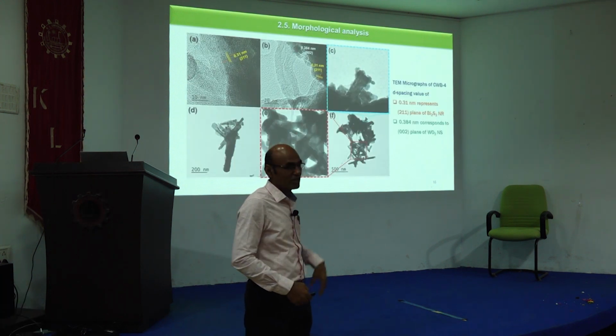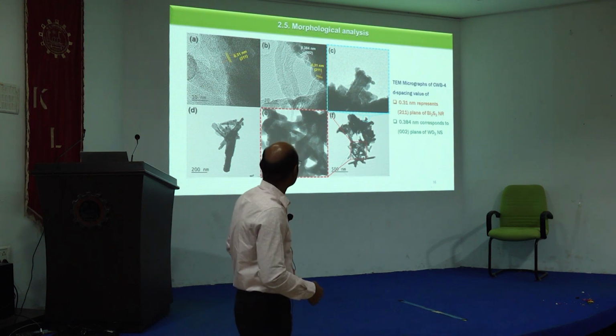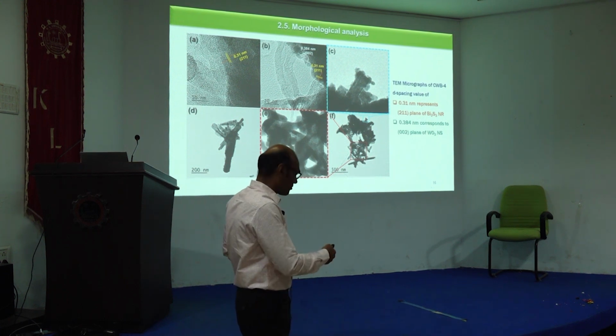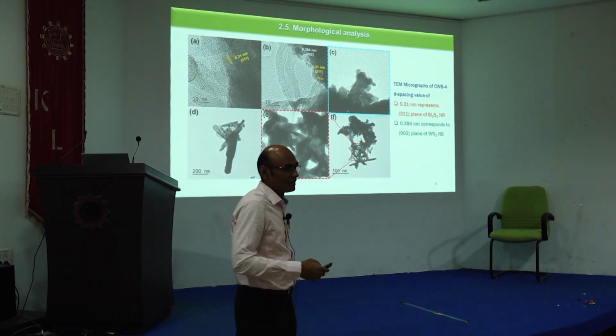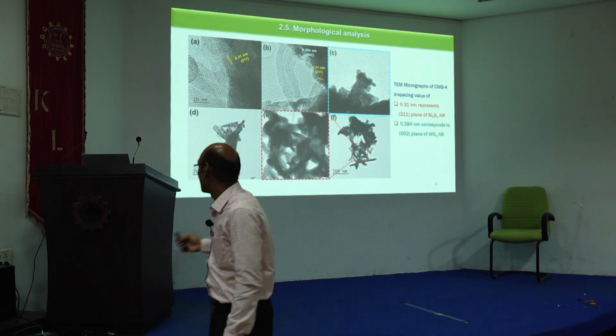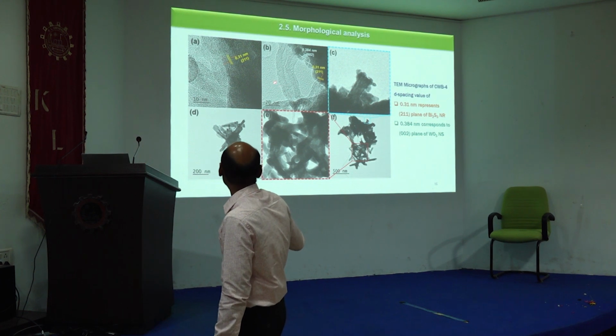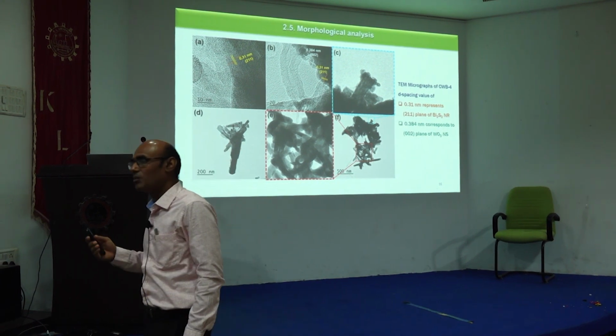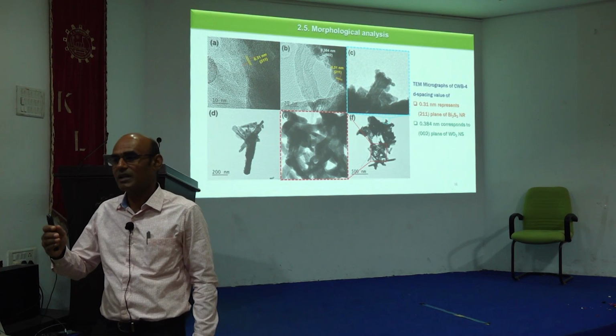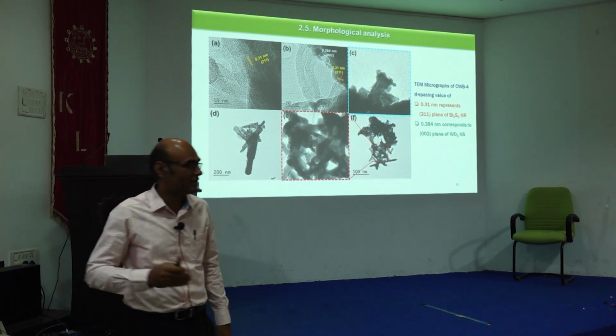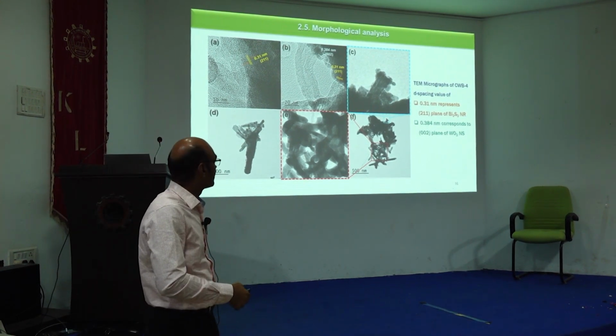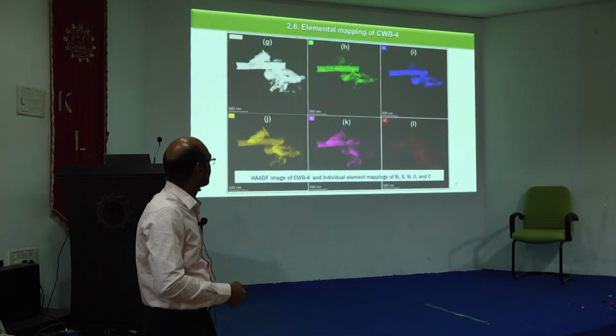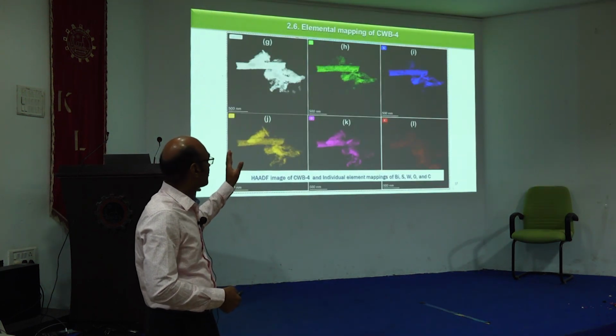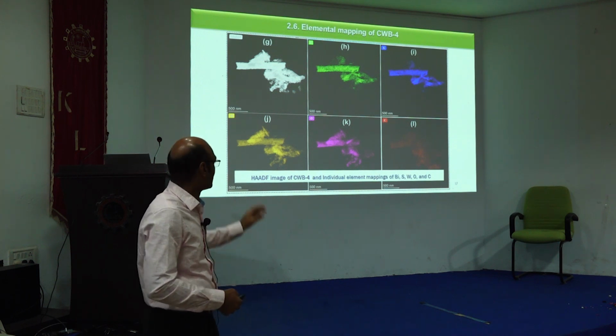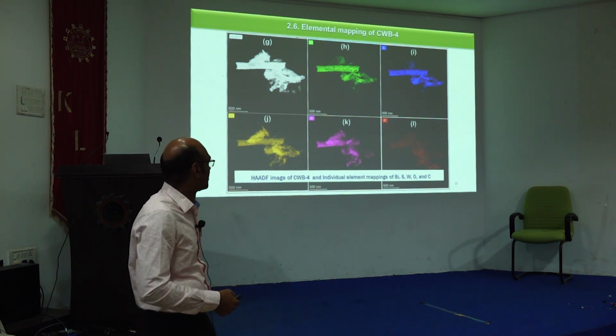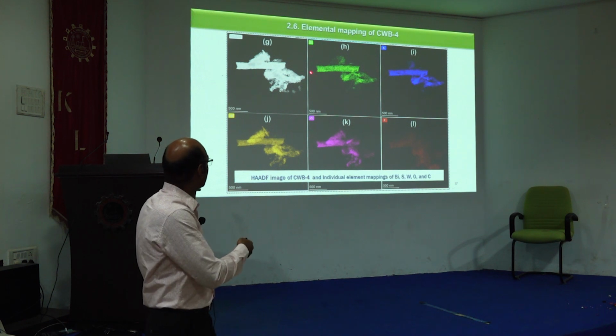And from HRTEM we also got interesting results, confirming from the lattice fringes the presence of the individual materials, and in the composite material the presence of both materials. So we can confirm that the prepared material has the required morphology, and it shows very interesting characteristics. The presence of these was also confirmed by using elemental mapping. This elemental mapping also gives very good information, with each color showing a different material.